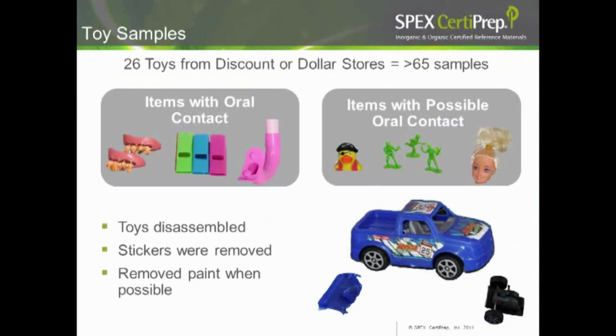The toys were disassembled into their different components of different polymers. So our truck here, the wheels were taken off, the silver seats inside were separated, the stickers were removed, and when it was possible, we tried to separate the paint from the underlying polymer and use that as a separate sample.